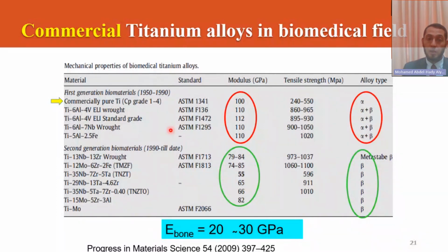And the next generation, which starts from 1990, beta type titanium alloys, can solve the problem: we have to avoid the toxic elements like vanadium, aluminum, and so on. And we substitute with niobium, zirconium, tantalum, and so on. Okay, and we have lower Young's modulus. So now we solved the problem, or rather, they solved the problem partially. The elastic modulus is much lower than the first generation, and all are beta type, and they avoid the toxic elements and so on.